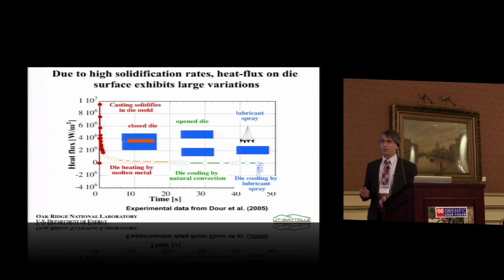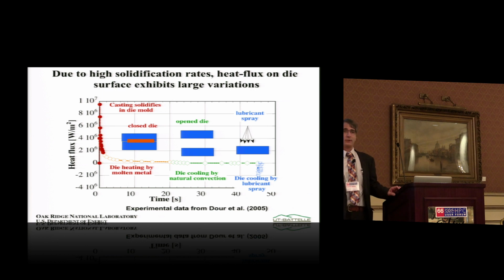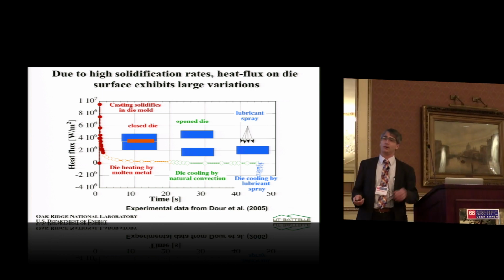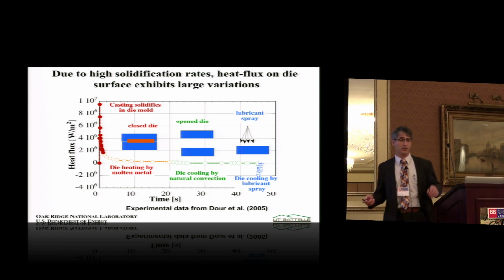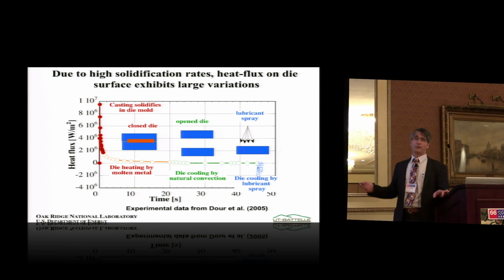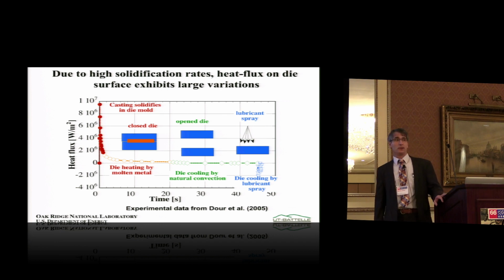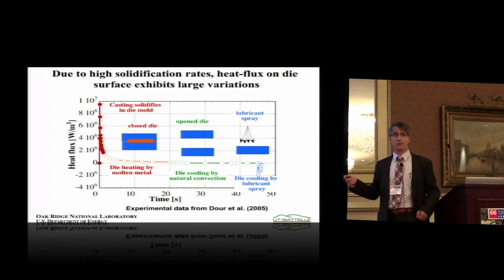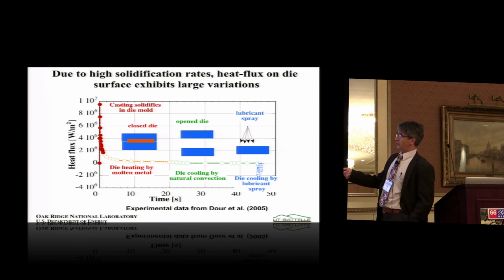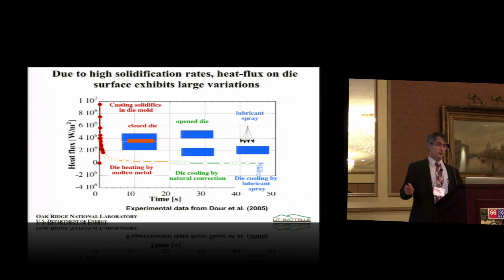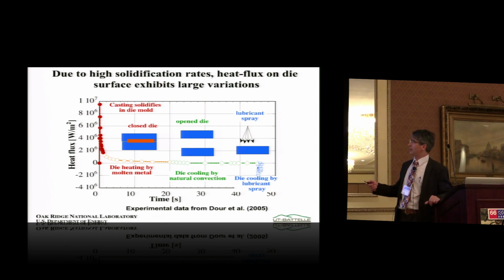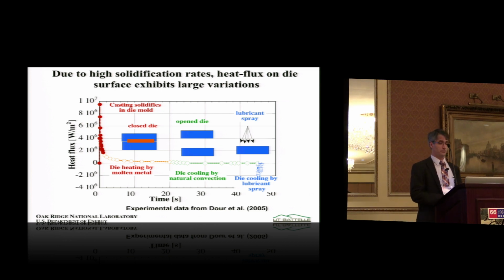So high pressure die casting, it's a very interesting process, and I took the liberty and digitized some experimental data that were presented in a paper. And you can see here the heat flux that's actually measured in situ. You get up to almost 10 megawatts per meter square. That's really a very high heat flux, but that lasts only a short while. The die is closed, the material solidifies, is kind of cartoon represented there by red coloring. Then you open the die up, you take the part out, and you have additional cooling of the die using lubricant.